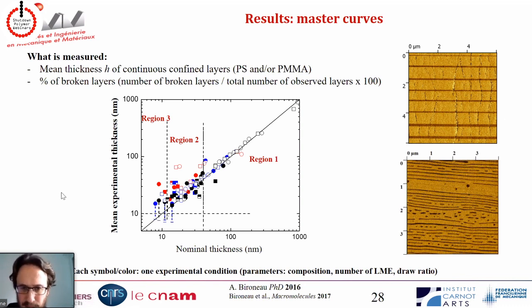And you can see that you have three regions. One is for layers that are above 15 nanometers. And you can see that there is a really good agreement for every experimental condition. So one shape and one color is one experimental condition, which I'm not going to detail. So there is a really good agreement for almost all the conditions we studied for layers above 15 nanometers between what we wanted to make and what we actually made. In the second region, there is some kind of scattering that appears, but some conditions work better than the others. In the third region, which is below 10 or 20 nanometers, you can see that we are always above the nominal thickness, which means that the experimental thickness we measure is always above the thickness we wanted to reach by choosing our processing parameters.